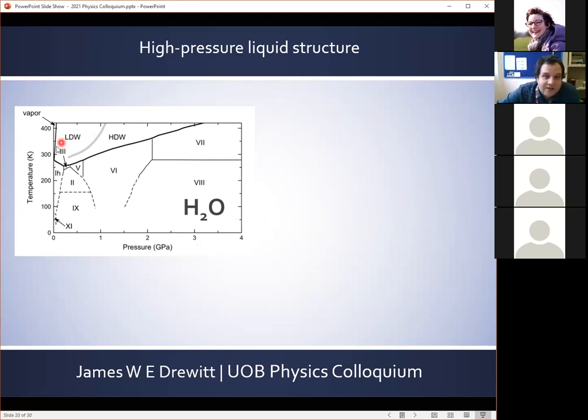And this negative slope on the melting curve can explain some of the remarkable properties of water, for example, the volume expansion from liquid water to ice at ambient pressure. And if we consider the Clausius-Clapeyron relation, the melting curve can be understood by the change in volume divided by the change in entropy. So for a liquid, the entropy is always greater than that of the solid from which it melts, and the volume change on melting is also usually positive. But if we have a negative melting curve, this implies an increase in density on melting.